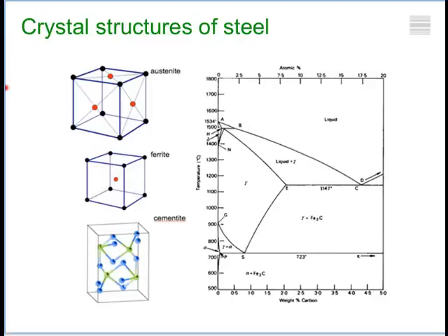It changes into a different crystal structure here, which we call body-centered cubic, because the iron atom is at the middle of the cube and also at the corners of this cube. And this is the so-called ferrite, which exists in the vast majority of steels, 1.3 billion tons of steels that we use today. Of course, the definition of a steel is that it contains carbon. And carbon combines with iron to form an iron carbide, which we call cementite, which has a very complicated crystal structure. It's a hard phase, and it's a brittle phase, but it's also a useful phase, as you will see later. So these are the three basic crystal structures which occur in all of the steels that you use today.